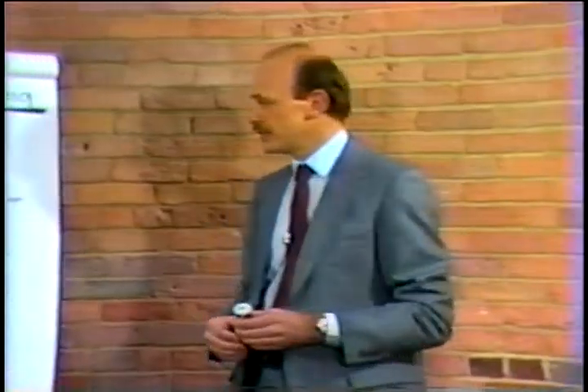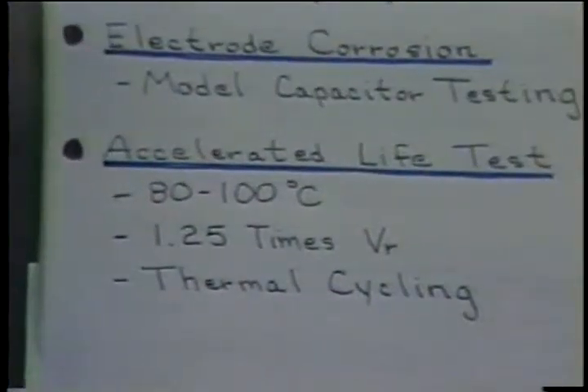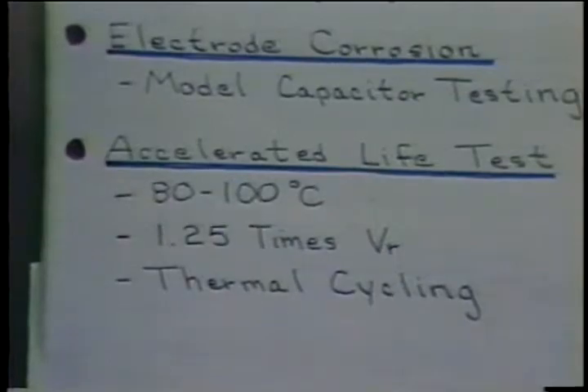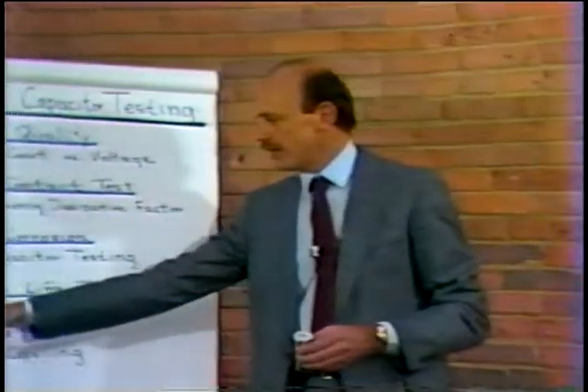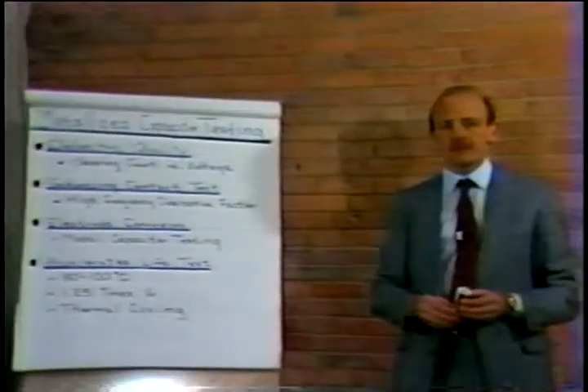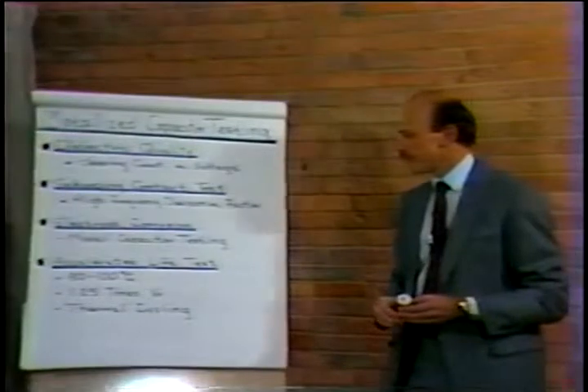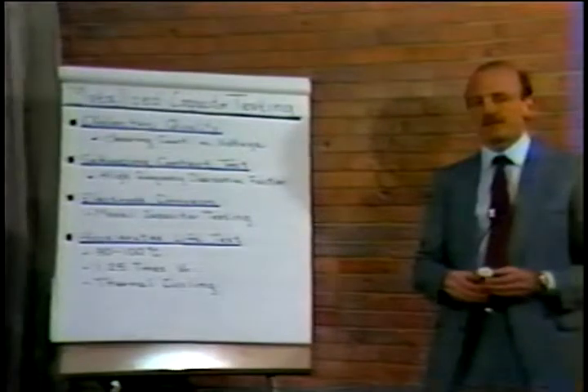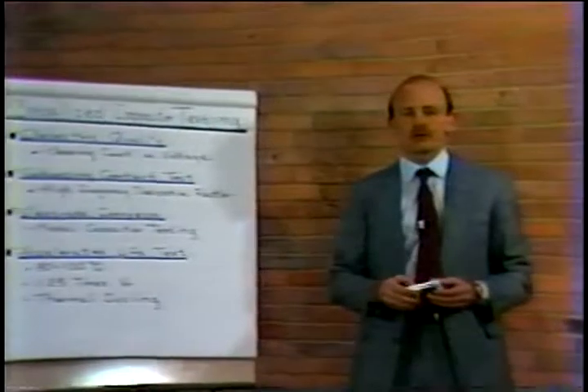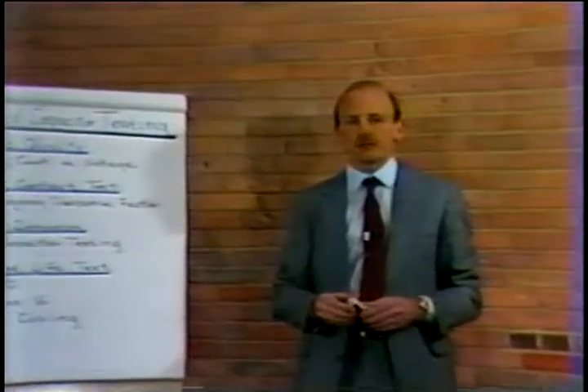But ultimately, the proof that a capacitor will operate, will work, and will provide reliable service in an application is obtained by an accelerated life test on a full-size capacitor roll, where we'll test the capacitor at 80 to 100 degrees C, which is 10 to 20 degrees higher than its operating ambient temperature, and an accelerated voltage of about 25% higher than the rated voltage. It is important that this test be thermal cycled in order to simulate the application environment.